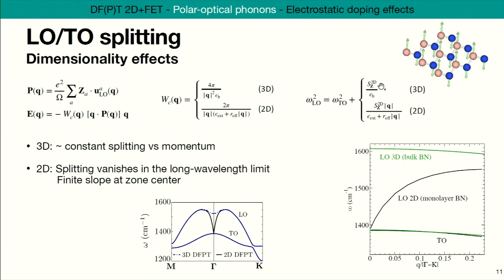So if you work out all those formulas, you can see that the contribution, this additional energy due to the dipole-dipole interactions, is more or less constant as a function of momentum in 3D. Essentially, it's the difference between this TO mode that we see here and the LO mode. It's a very well-known condensed matter mechanism called LO-TO splitting, and the splitting is constant. In 2D, however, the splitting is not constant anymore. It vanishes at zero momentum, so at zone center here. And it starts with a finite slope here, which is very peculiar, because if you look at a path in the Brillouin zone that goes through the zone center, you end up with this discontinuity in the first derivative.